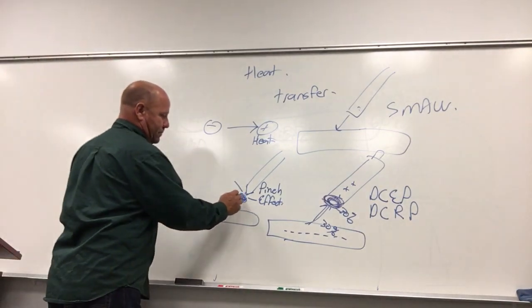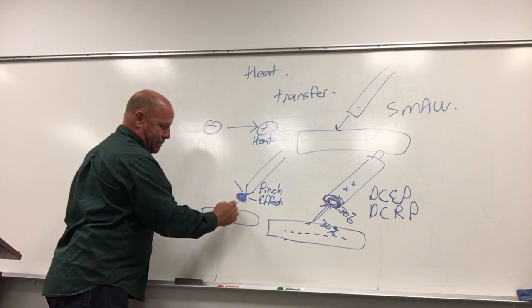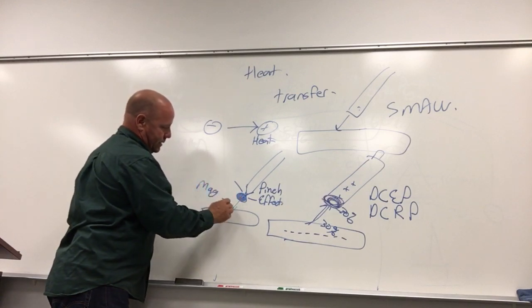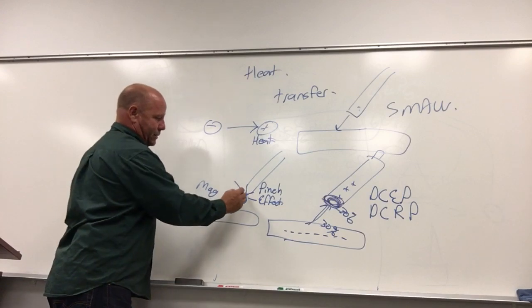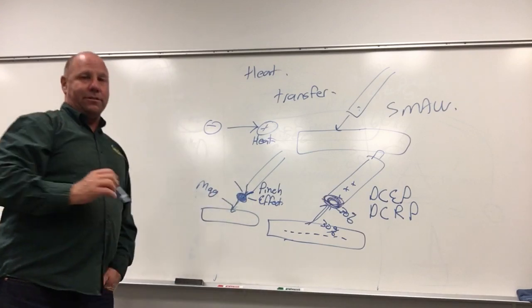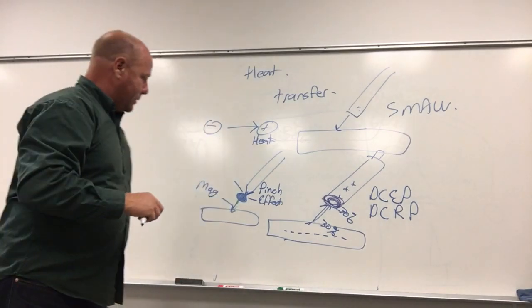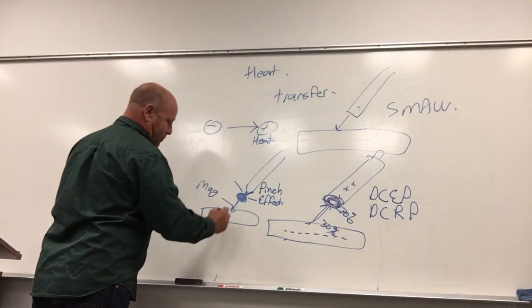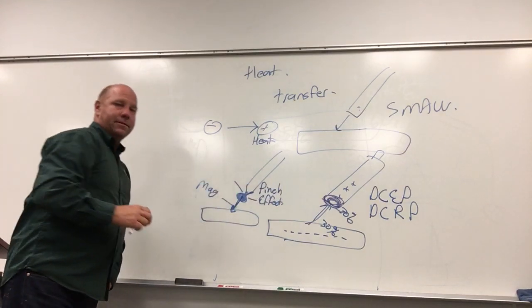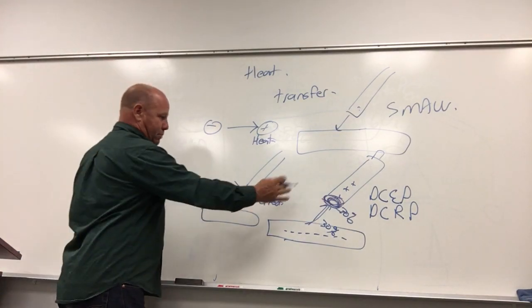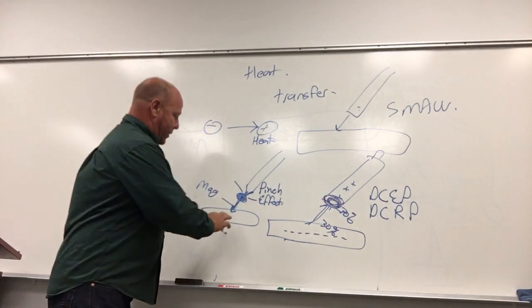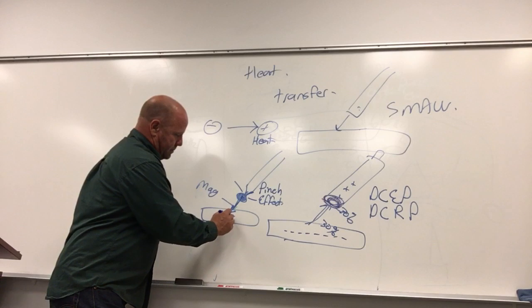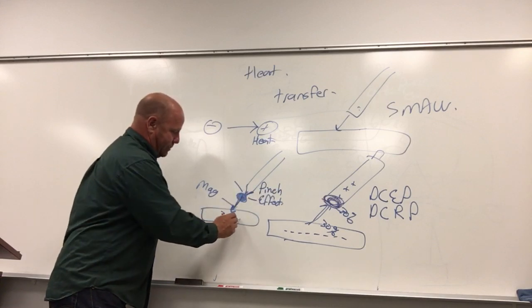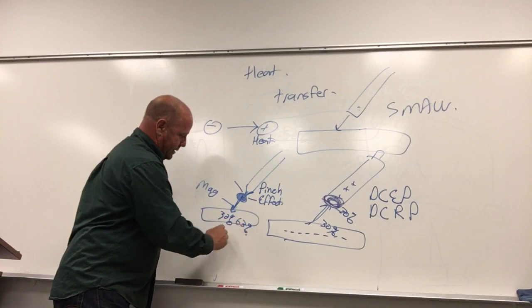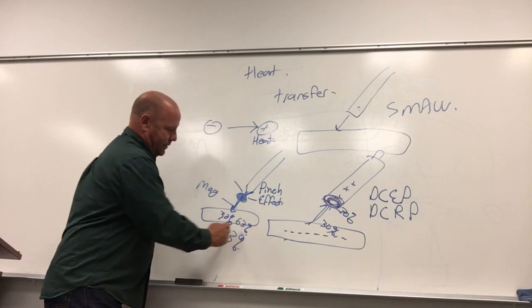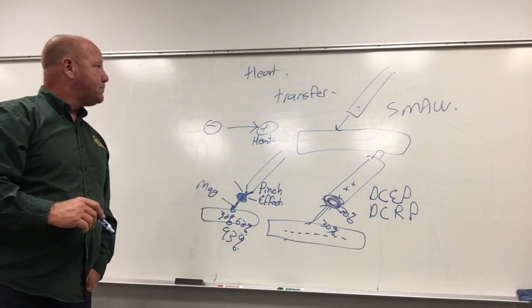This little ball gets hot. The force is the magnetism, pulls it down, and eventually this force becomes so great that it counteracts its tension with the rest of the electrode, and the ball falls into the puddle. When this ball comes across into the puddle, it brings all that heat with it. 90+% efficient. So we already had 30% of the heat here. 90+% of 70 is going to put us at another 63. So now we have 93% of the overall heat generated on our plates.